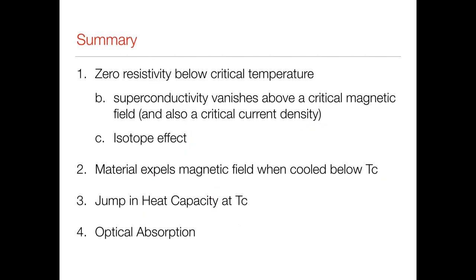So I just wanted to finish with a summary. This is the same summary slide we had in the first superconductivity lecture, and let's just check that we can understand things. So we know experimentally zero resistivity below a critical temperature. Okay, we now know that's because of the formation of Cooper pairs, where there's an attractive force between electrons mediated by their lattice. We also know that superconductivity vanishes above a critical magnetic field, and we've been able to understand that in terms of a critical current density that flows in the material, whereby there can be enough momentum to give enough energy to break apart the Cooper pairs.